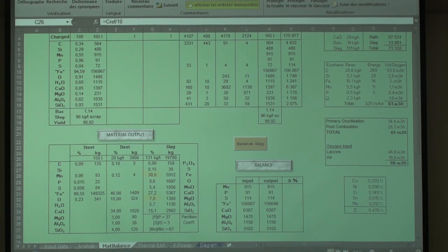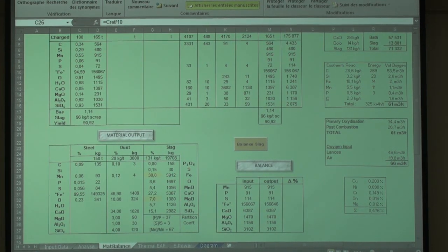Okay. So now you know that in conventional furnace, the first slag is over-oxidized. And the only way to reduce this high FeO in the slag is to inject carbon. So that's why I'm not so, let's say, friendly with the practice to burn the door as fast as possible. Because then you facilitate this oxidized slag to escape the furnace. And then you have yield loss on top of more air ingress through the door. So in fact, it's better to keep the door closed as long as possible.